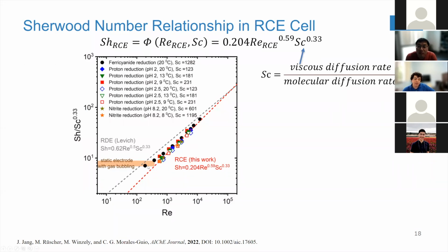And what we have determined is this red line that is a universal line for any electrocatalysis that we do in this system, right? What this means is that any electrocatalysis that we do, they are all riding the same hydrodynamics as we change the Reynolds numbers, as we change the rotation, and as we change the temperature of the system. So what this means is that the system is well characterized, and now we can look confidently at different chemistries, but we know that they all have the same hydrodynamics.